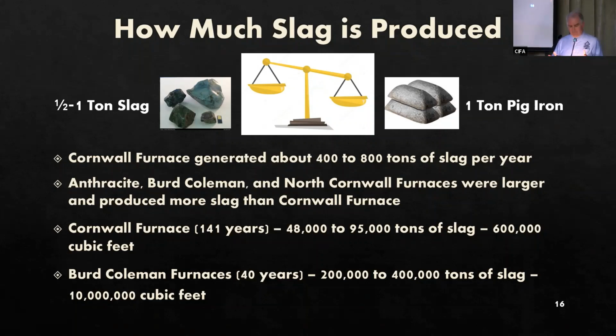So at the Cornwall Furnace, which generally produced about 3 tons of cast iron a day and operated nominally about 9 months out of the year, Cornwall Furnace would have generated between 400 and 800 tons of slag a year. The anthracite, Burd Coleman, and North Cornwall furnaces were much larger, so they would have generated much larger quantities of slag. So, for example, in 1880, Cornwall Furnace produced 675 tons of cast iron. That was 3 years before the furnace closed. So that was about the peak of their production.